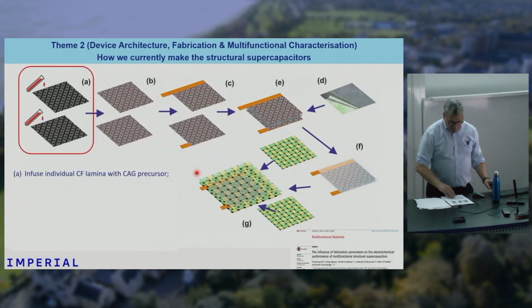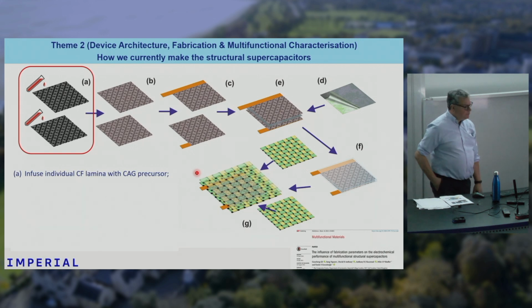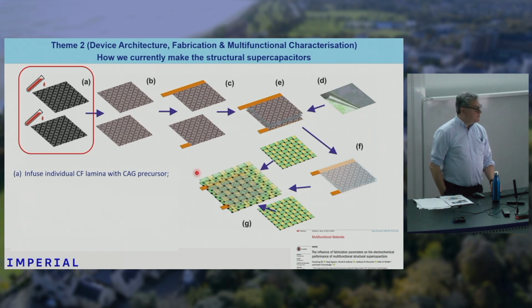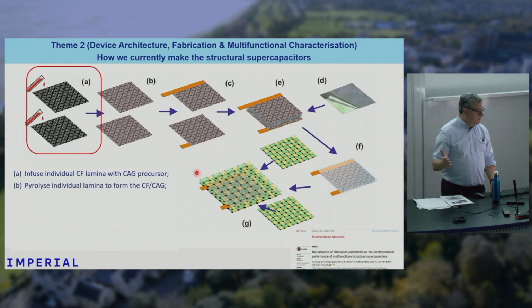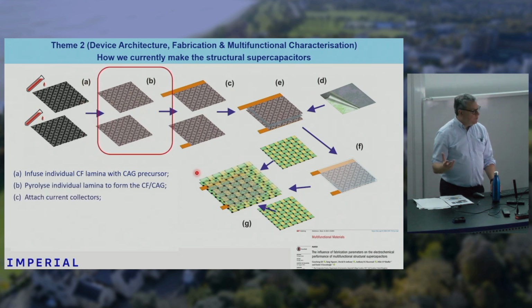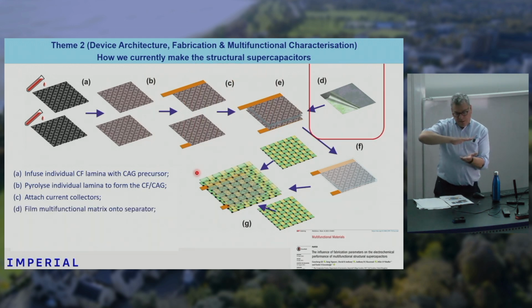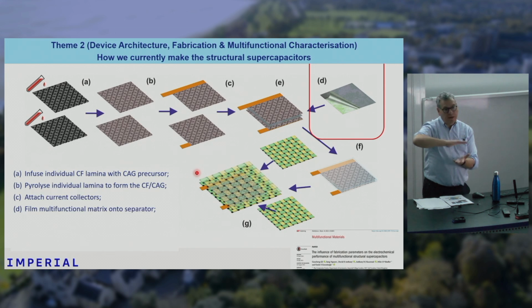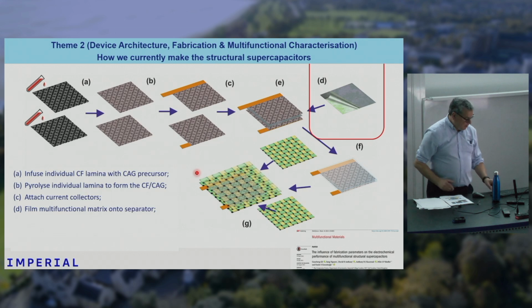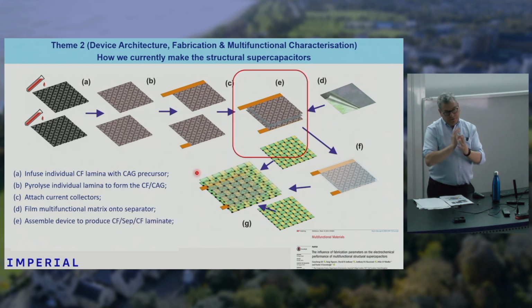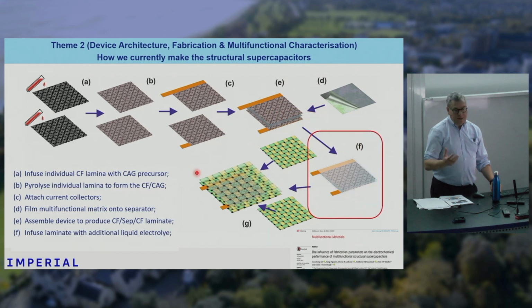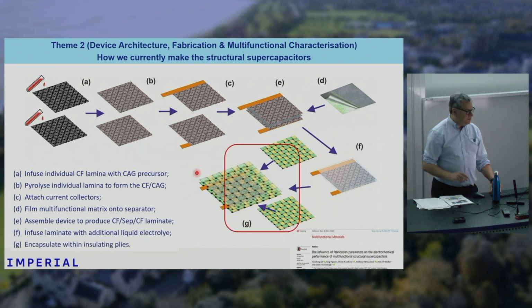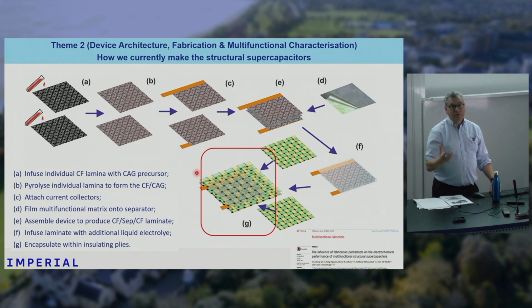So let me talk through how we make our devices and show you some of the challenges that that's presented. We take the individual electrodes and we infuse them with the precursor for the carbon aerogel, do the pyrolysis to produce the carbon aerogel, put on the current collectors, and then we take the separator and we film a layer of structural electrolyte onto that. So we assemble that whole device, consolidate it, and cure it to produce the final device, as shown here. But that final device has carbon fiber layers which are electrically active. We can't just leave that out on the desk. It needs to be encapsulated. So the next stage is the encapsulation of that device within an electrically insulative layer.